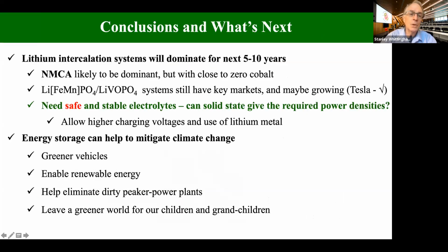To conclude on what's really next, a number of people are saying, well, what's beyond lithium ion? I think the consensus in the field is that lithium ion will dominate for the next 5 to 10 years. And I didn't show you the slides of what's happened to the cost of these batteries, but they've dropped from over $3,000 a kilowatt hour 5 to 10 years ago to about $110 today, and are predicted in the next 2 or 3 years to be about $50 a kilowatt hour. So any new systems clearly have got to get to a lower cost. So the layered oxides are going to dominate. These will probably have less than 10% cobalt and a good chance of no cobalt in them.